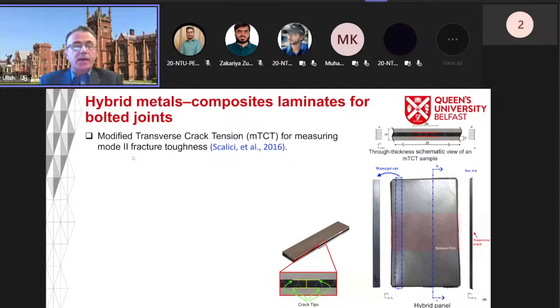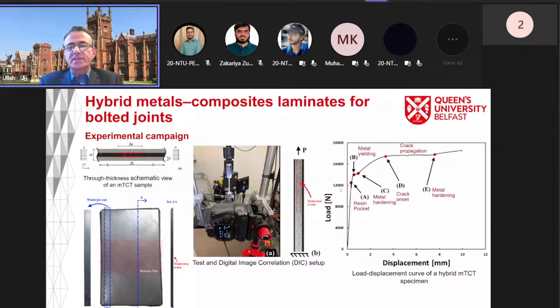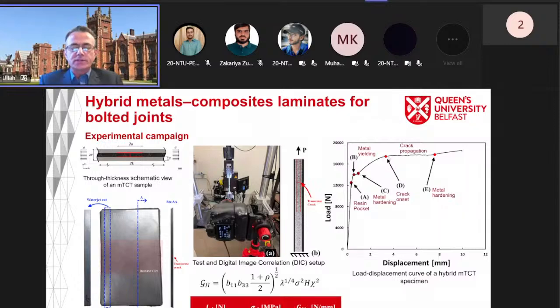And just to show some of the experimental results here, this is how the load displacement looks in this particular case. Because in this case, we have this transverse crack in the middle. So first, when you apply tensile load, first this transverse crack, which is just matrix material there, will break, and then there will be some hardening, then there will be some plasticity of the metal part, and then some hardening again of the metal part. And at this point, which is the most important point here, the crack will start to propagate. And this point will be our maximum load, that is what we will record here.